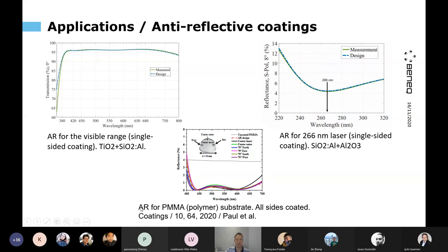And here is another example of an anti-reflective coating on a 50 millimeter diameter PMMA, so polymer, object, a highly curved object, coated on all sides. Maybe a little bit difficult to see, but one of these curves here is the design, the red dashed line, and all the actual measurements at different locations around the object show performance very close to the designed film. So it's showing that the film is rather uniform everywhere.